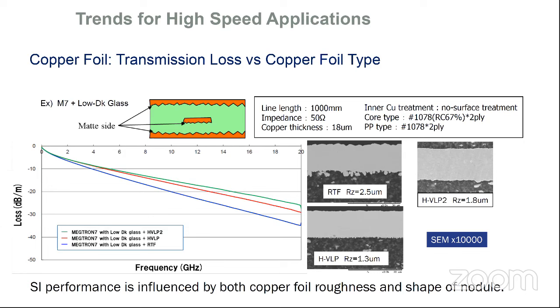But at this point, I think I need to inject that there's no free lunch here. When you start to work with smoother and smoother copper foil on your core material or the substrate you're making your inner layer with, there's going to be an experience shift or challenge on getting dry film adhesion to be as good as it needs to be to retain the kind of print and etch yields that you're accustomed to.